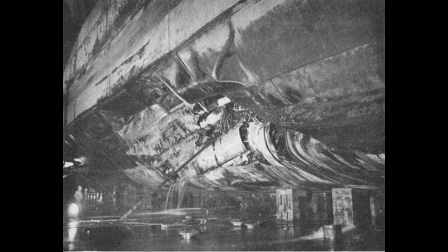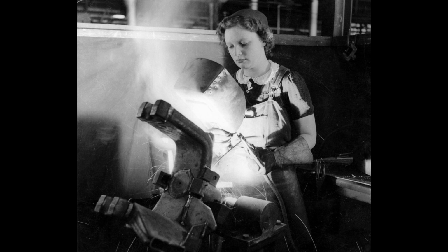The reinforcement straps welded onto the hull sides had performed exactly as designed. Several had cracked completely through, absorbing energy and preventing fractures from spreading to the main hull plates. This was sacrificial engineering at its finest. Design deliberate weak points that will fail first, protecting the critical structure behind them.